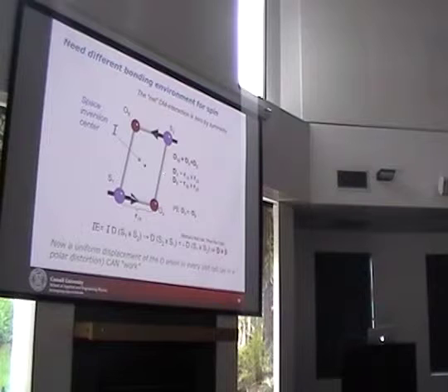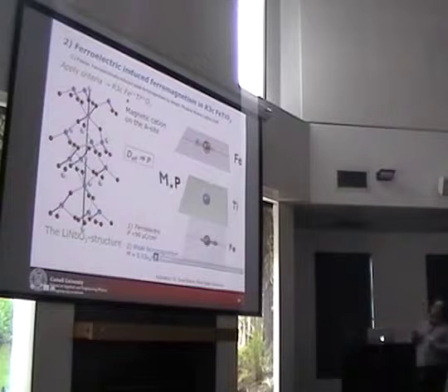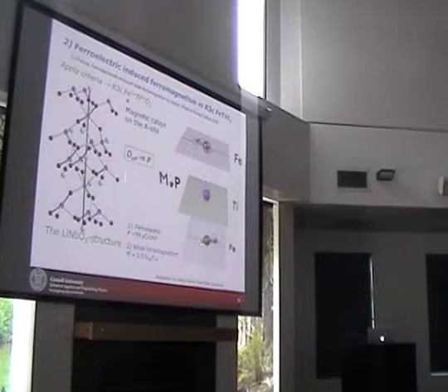So if I can find a motif like this with an inversion center between the two spins, I know from very simple symmetry arguments that the net DM interaction has to be zero. If I remove that symmetry, that inversion center, such that, for example, a ferroelectric distortion would, I'd bias one of these pathways over the other, and I would bias one sign over the other, and the net DM interaction would change sign. And that's exactly what we found in this realization: iron titanium O3, in the lithium niobate structure.